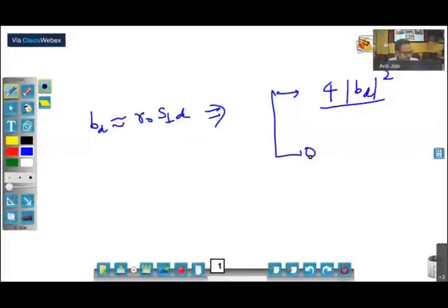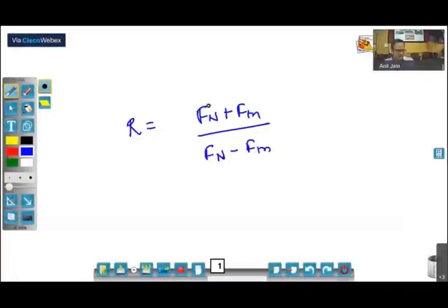In a typical experiment using a polarized neutron beam, we go to some Bragg peak and try to measure the intensity of this peak in the flipper off and flipper on condition. What we measure is the flipping ratio, the ratio of intensity for flipper off to flipper on.